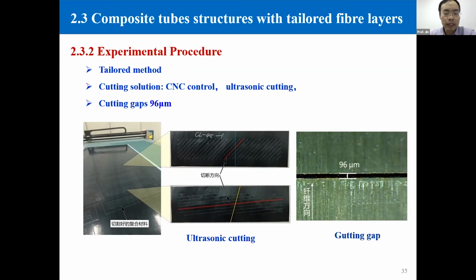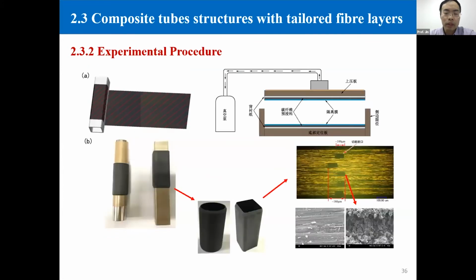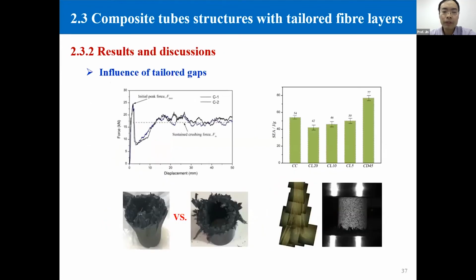The pre-preg is cut using an automatic machine, and we define a cutting angle between the cutting direction and the fiber direction. Then we roll the pre-preg and use the RTM process to get the composite tube. After curing, we also inspect the microstructure of the tube, and we found in the structure the fiber was cut. And now we focus on the performance of mechanical properties.